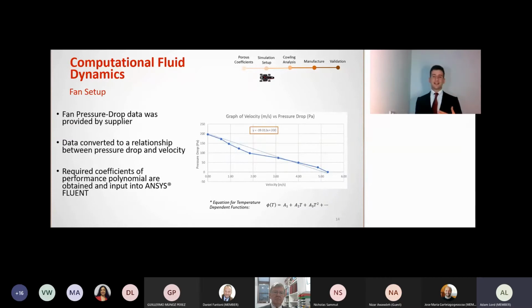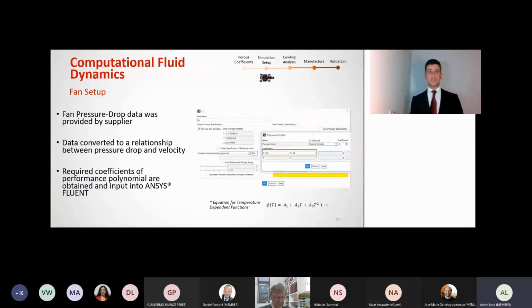The fan itself was declared as an internal fan zone, and this was modeled as a specified pressure jump. This was done by first obtaining the pressure drop data sheets provided by the fan manufacturer, and this could then be converted to a relationship between the velocity and pressure drop, much like the approach taken to the radiator itself. Like this, the fan's behavior could be defined in terms of a polynomial profile, and using the standard equation for temperature-dependent functions, it could then be modeled into Fluent.